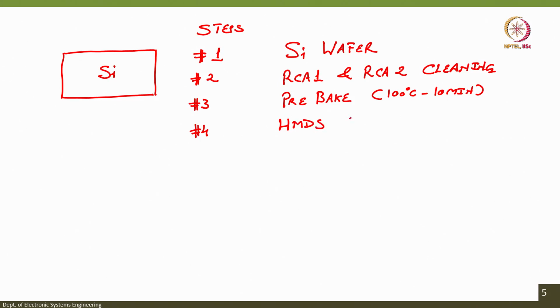Next step is HMDS coating. This will improve the adhesion of the photoresist onto the silicon wafer. Next step is photoresist coating. Whether the HMDS coating or the photoresist coating, it is done using a system called spin coater, the spin coating machine. So, silicon wafer cleaning, pre-baking, HMDS coating, PR coating.